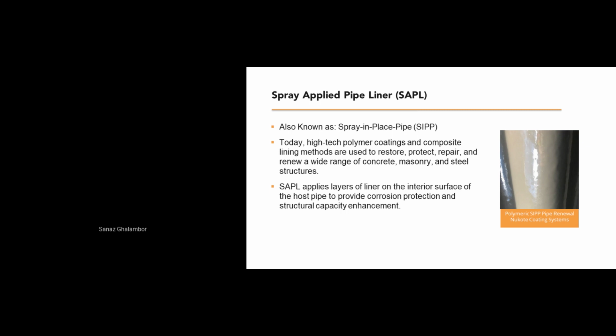SAPLs are different from conventional coatings because coatings are considered barriers for corrosion protection, but linings are used for both corrosion protection and structural enhancement. SAPLs are applied in layers, so we apply layers of the liner on the interior surface of the host pipe to provide a new polymeric pipe and provide corrosion protection and also structural capacity enhancement.